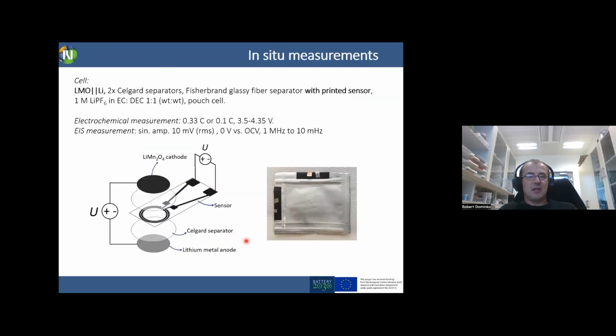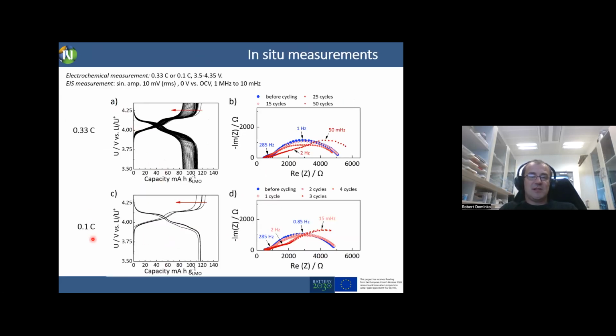So I already mentioned that we cycled electrodes, and here I will show you the cycling of a lithium metal, lithium manganese oxide spinel structure battery with the sensor inside. We cycled those batteries with different C rates, and with the slower rates, we see a faster response of the sensor. This can be understood in two different directions. One is that the cell stays much longer in the high oxidation state, and we know that dissolution of manganese occurs at these high oxidation states, so it's correlated with the lifetime of the cell at high oxidation, compared to when we are cycling the battery faster.